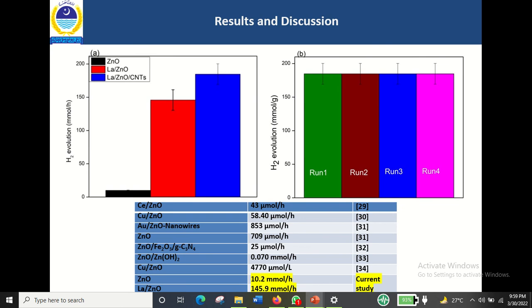And the table at the bottom shows a comparison of the current study with the previously reported work. It is clear that in our study, zinc oxide in pure form produced 10.2 millimole of hydrogen in an hour, lanthanum ZnO produced 145.9 millimole of hydrogen in an hour, and lanthanum ZnO carbon nanotube photocatalyst produced 184.8 millimole of hydrogen in an hour.